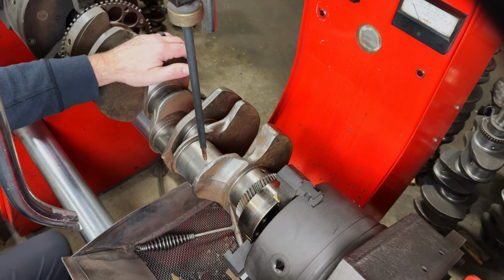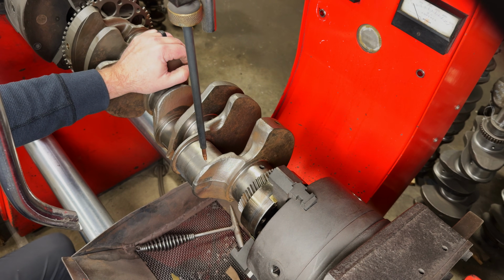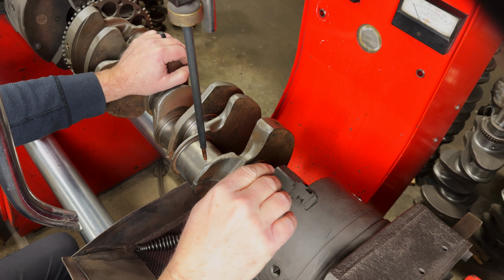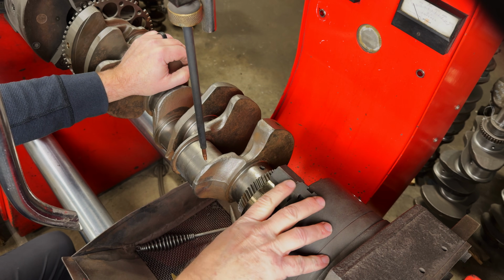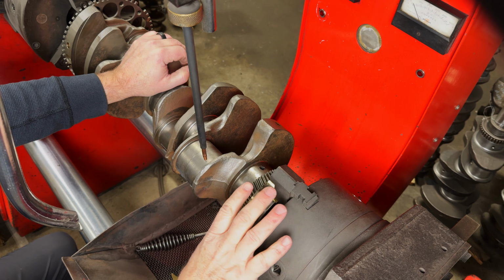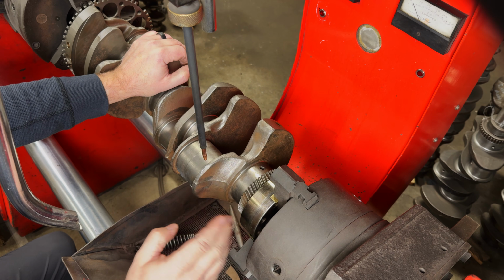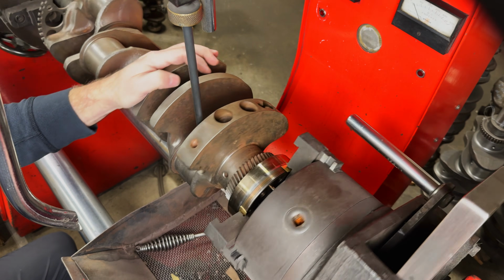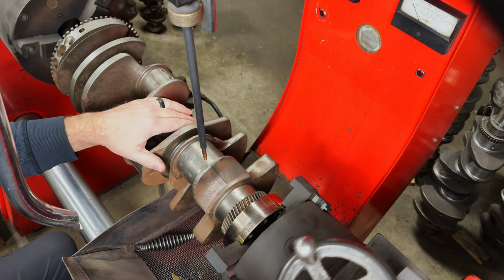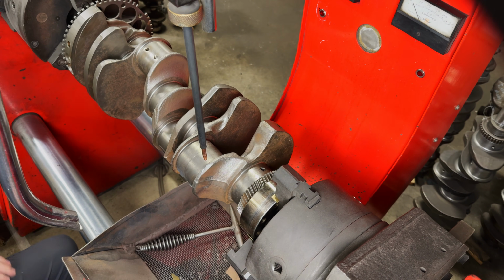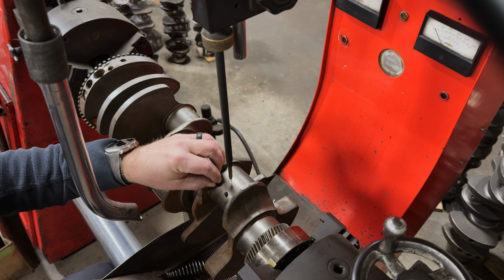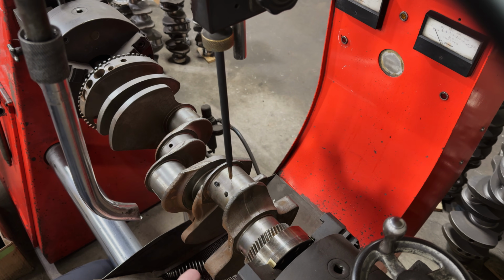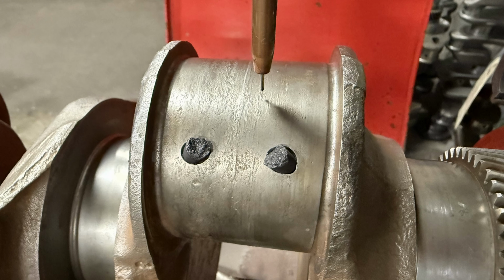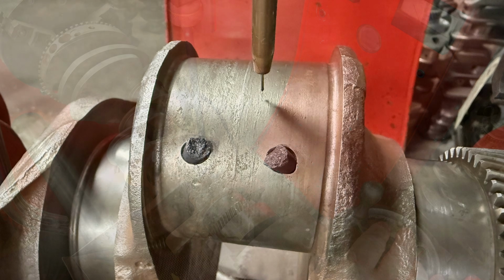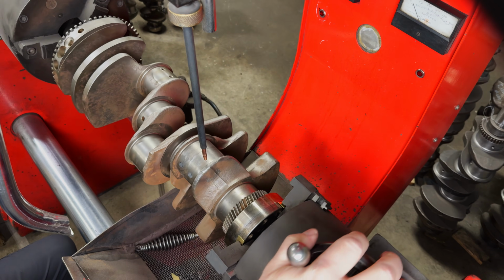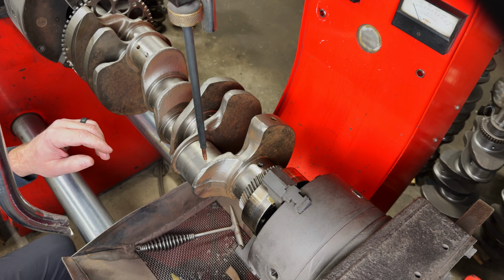We have our Power Stroke Stroker project loaded up in our crankshaft welder. This welder uses offset chucks, similar to that of a crankshaft grinder. Those allow us to shift the axis so it's centered on the rod journal. That's why you see it running true to the connecting rod axis instead of the main center line of the crank. We've gone through and plugged the oil galleys so that weld debris doesn't get into those passages. We'll still need to reopen and chamfer those holes afterwards, but it keeps the process much cleaner and gives us a better end result.